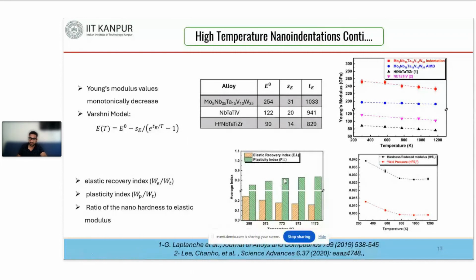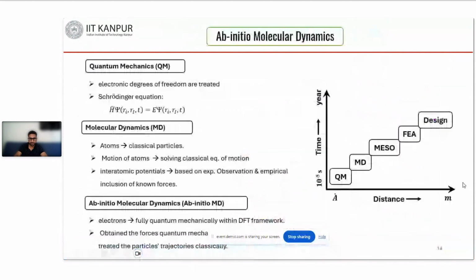So we can say that plasticity is behaving like this: initially the hardness is dropping, the plasticity is increasing, and then there is a stable plateau region. Similarly, we have measured the hardness to reduced modulus ratio and yield resistance pressure. They are also giving similar behavior to the hardness behavior.